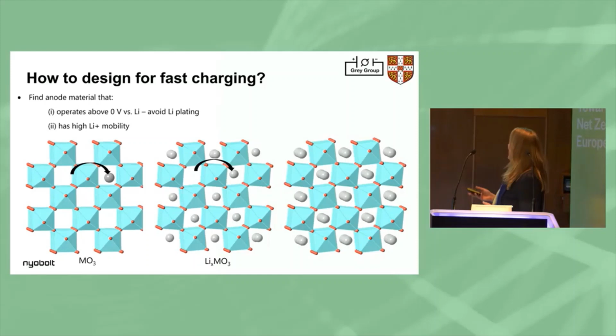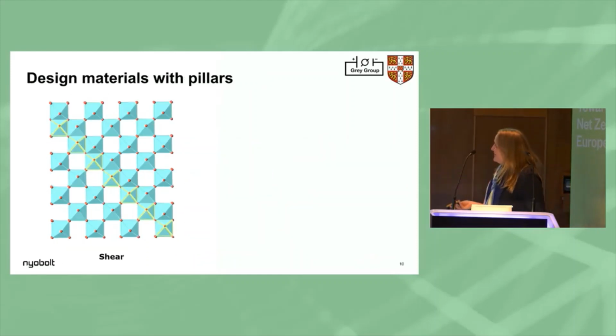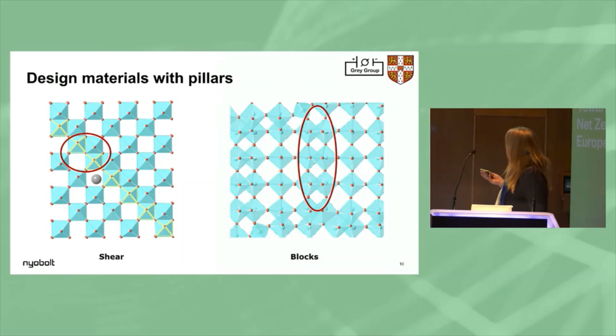I'll keep going. But yes, they looked at how they could design optimum structures, so materials with pillars that can prevent this disordering and the ions getting stuck. So they looked at these shear structures where you end up with these pillars that can prevent that disordering, and also the block structures. So again, looking at really stabilizing that structure with the insertion of lithium ions and enabling that movement in and out as it's going.